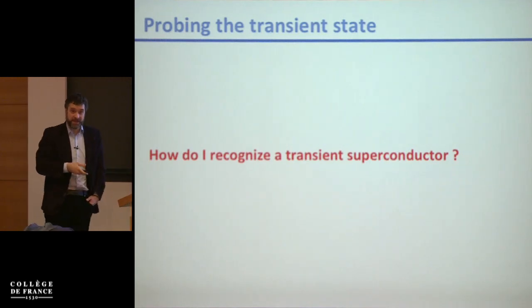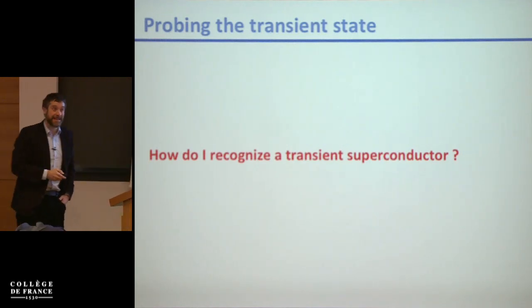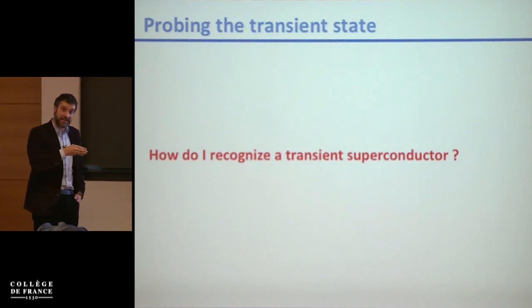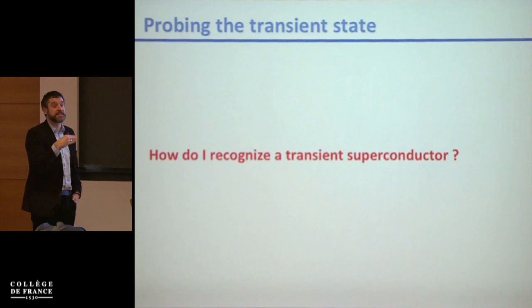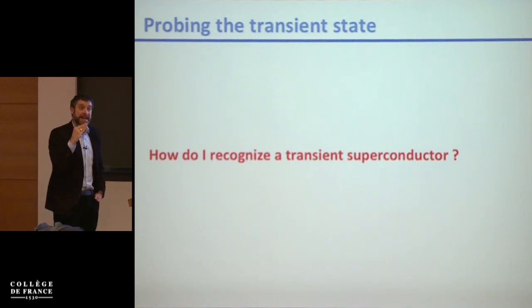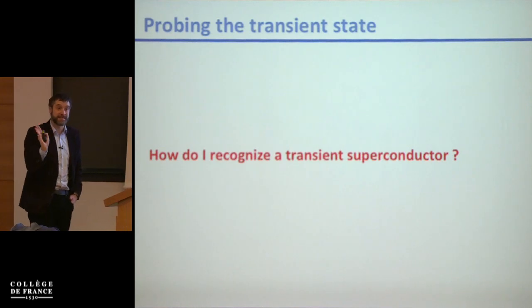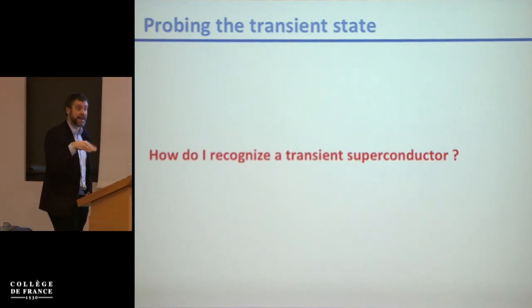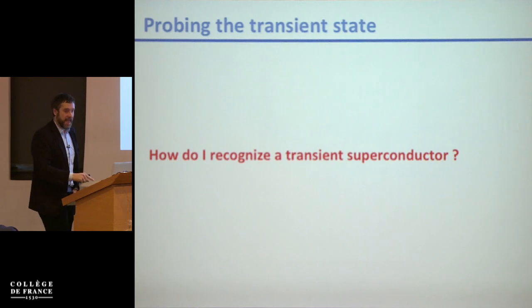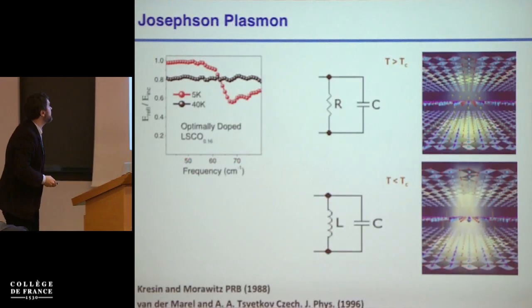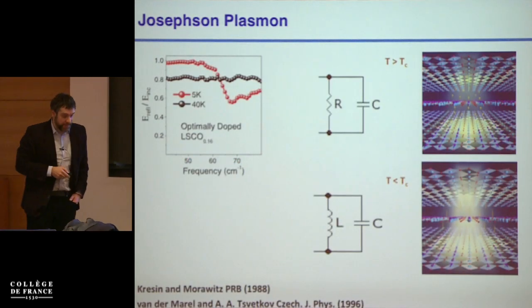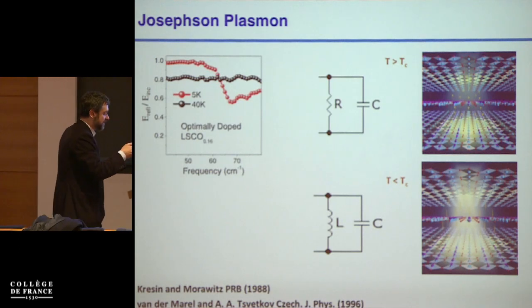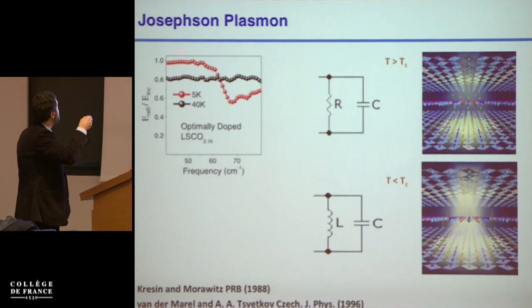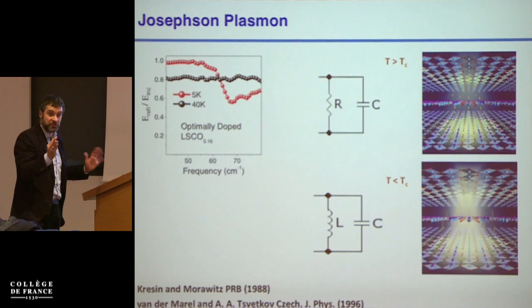which from its magnetic properties, of course, because it's a DC diamagnet, and because it has a zero resistance at zero frequency. And everything else that I see at finite frequencies is indirectly related to the superconducting state. But there are some features that, at least at equilibrium, are considered one-to-one synonymous with superconductivity, just anecdotally, let's say. And one of those is the observation in the optical properties of these cuprates of these plasma edges at about 1 to 2 terahertz frequencies.